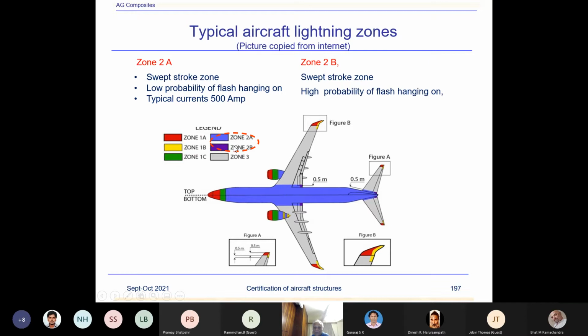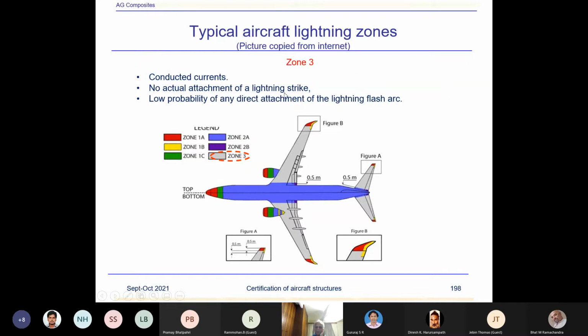Then zone 2, which has much lower current levels, of course. So the damage created if lightning strike occurs in these zones is much less. Zone 2A is a swept stroke zone, low probability of flash hanging on, typical currents 500 ampere. Zone 2B, swept stroke zone, high probability of flash hanging on. Then zone 3, which has a very small level of current, in fact conducted currents, no actual attachment to lightning strike. Zone 3 is essentially these surfaces. So very little damage is created, because they are not very high current, with low probability of any direct attachment to lightning strike.